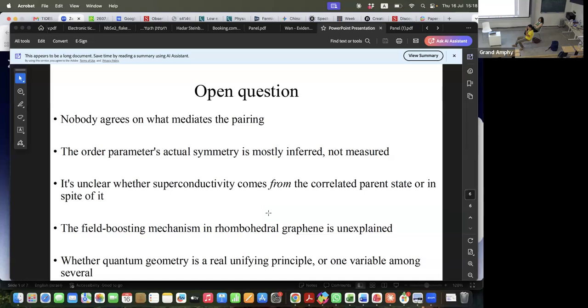This kind of stuff is a bit tricky because, as I said, this material kind of relaxes to Bernal. Though if you look into papers, they will say that Bernal is less favorable energetically than rhombohedral. But the truth is that most of the time our problem is that it gets relaxed. And Andrea has, for those of you who are interested, a paper now on arXiv to maximize the area and have a process to make the stack that is way less stressful. But what Yuval is saying is possible in theory. In practice, maybe in 100 years.